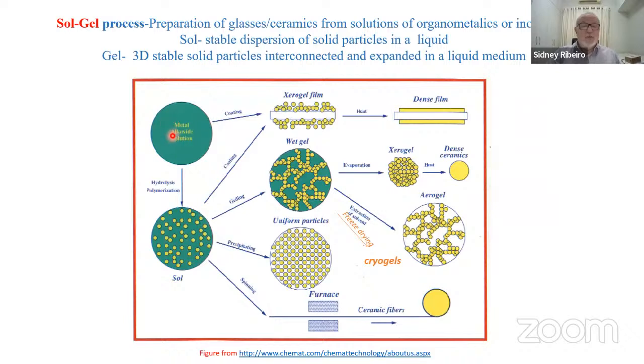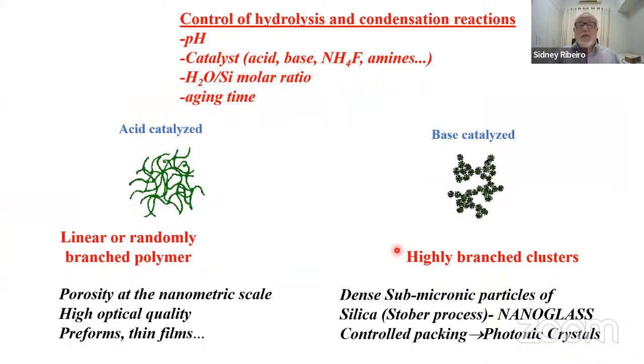This summarizes it again. We have our precursor, we hydrolyze it to obtain the sol. And from the sol, we can do a lot of things. We can do coatings in order to have what we call a xerogel film that we can densify. By gelling, we can have particles. From these particles, we can obtain the xerogel or the ceramics. We can precipitate in the form of uniform particles. We can spin the solution in order to have fibers. We can dry in supercritical conditions in order to have what we call aerogels, or freeze dry in order to have cryogels. So a lot of different materials can be obtained.